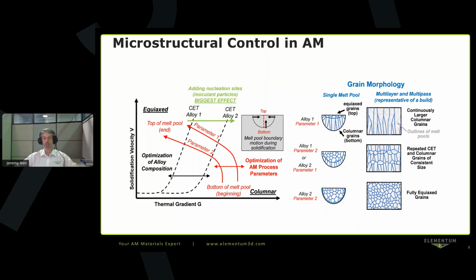You can also change your process parameters. If you change your laser parameters, your power inputs, your travel speeds, things like that, you can control your solidification microstructure within a certain extent. However, those process parameter changes also do affect your production speed, so you can slow down your production, which isn't very desirable if you're messing with those too much. But also within a given process like laser powder bed fusion, you are sort of limited to a window that works well, and you can't completely change your solidification structure generally within that window that works well.